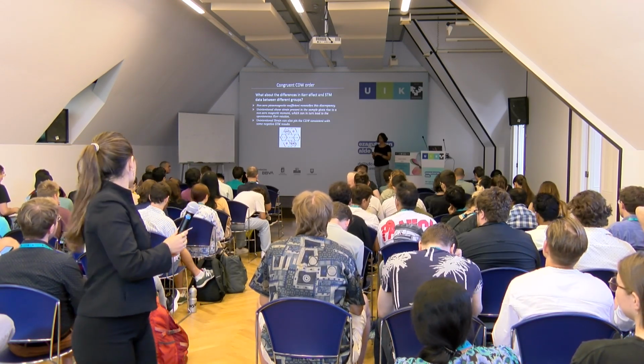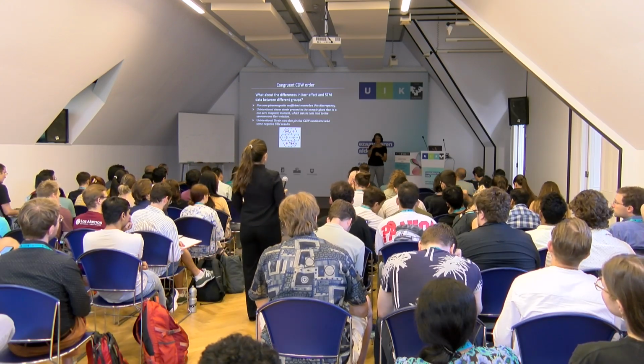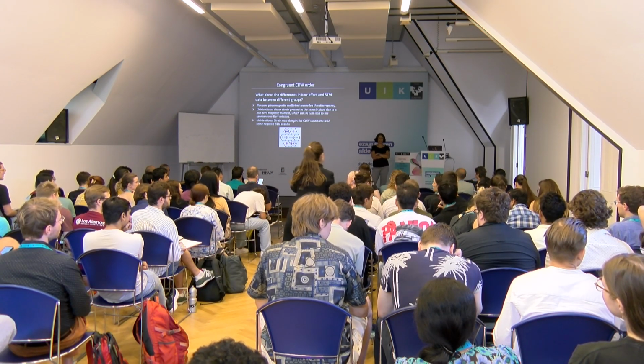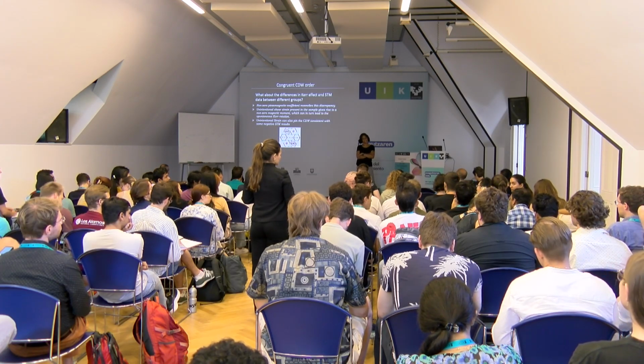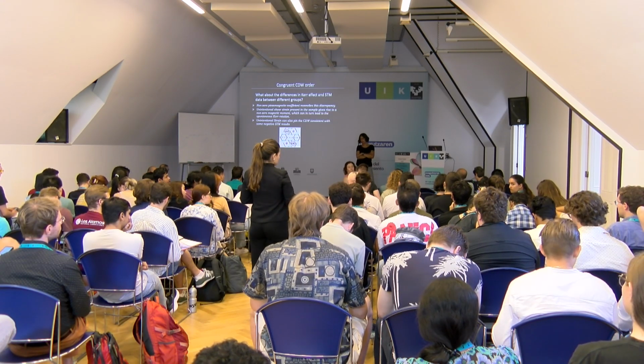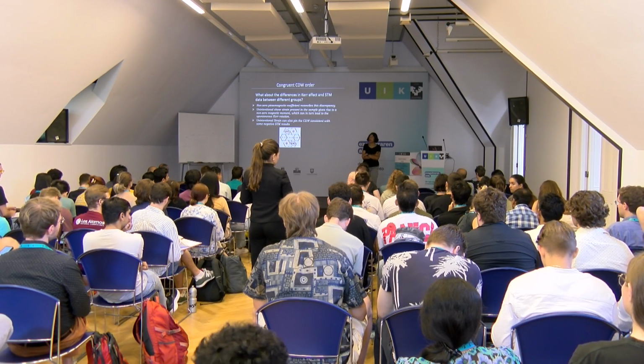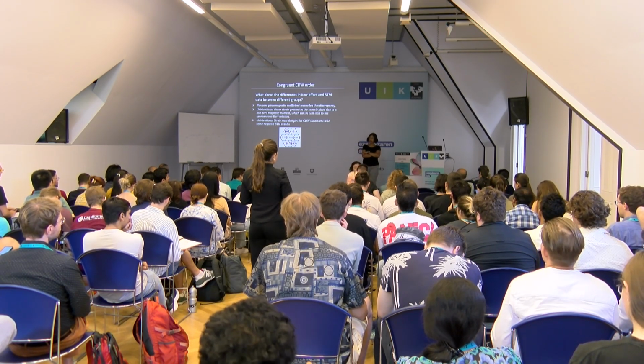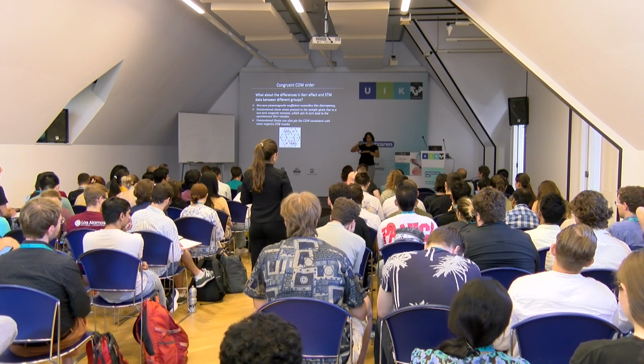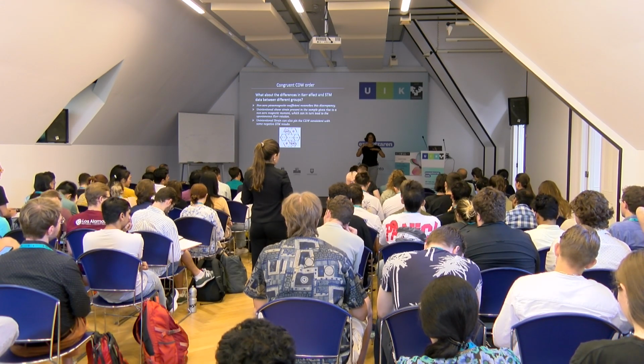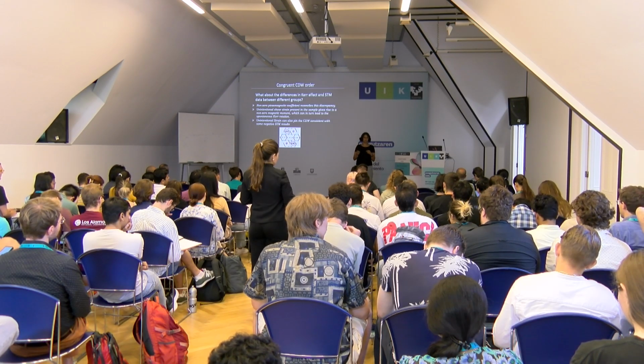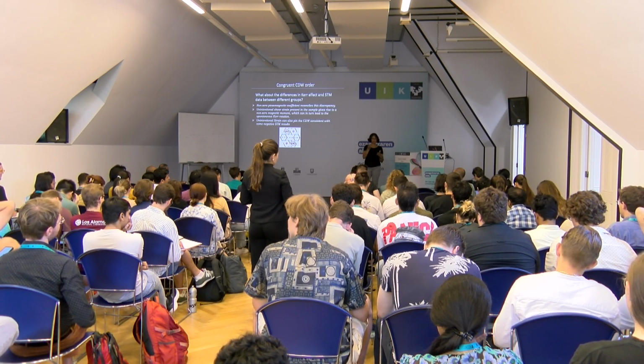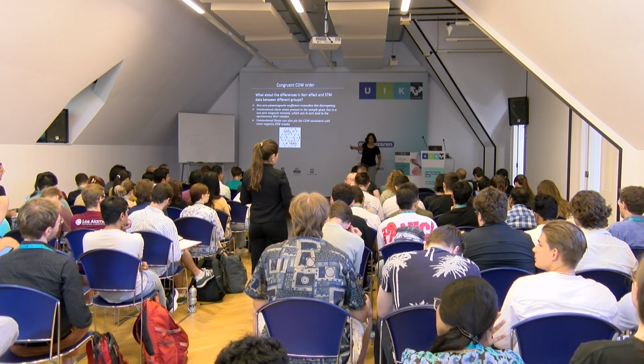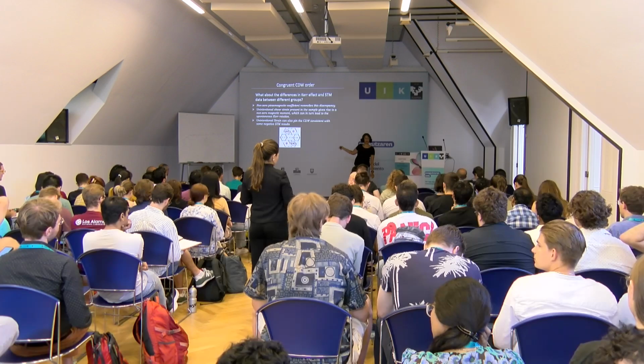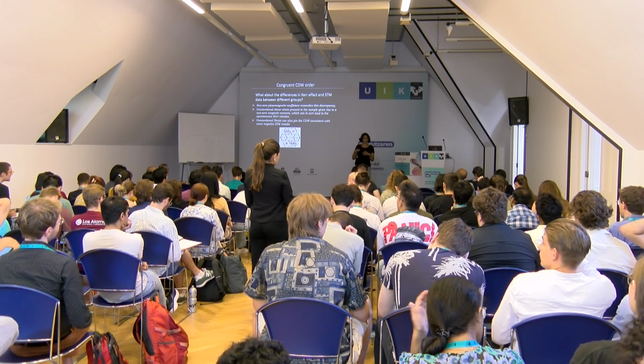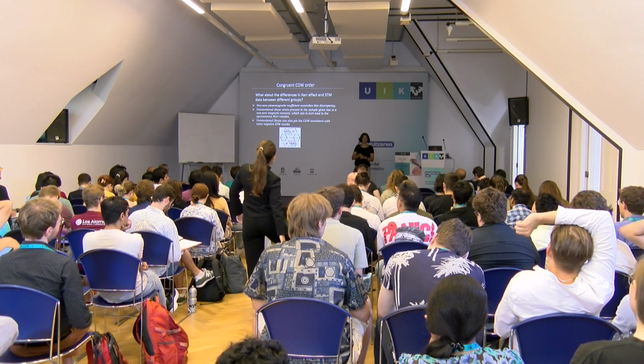Okay, so should I go forward? I have at least 10 minutes. Sorry, one question. Then according to you, in the complete absence of strain or magnetic or electric fields, you recover the six-fold symmetry? Without the staggering. This material has the staggered CDW, so that picks one direction out of the three. So you don't fully recover rotational symmetry, but you should have mirror symmetry, yes. In this particular sample, you won't get the rotational symmetry back. But in other samples, without the staggering of the charge density wave, you will recover your six-fold symmetry.